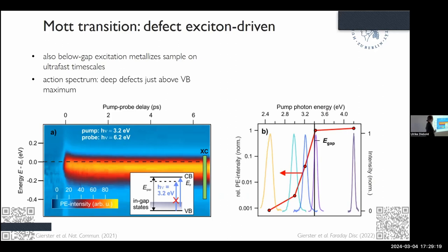And this means that the states responsible for this must be sitting really just on top of the valence band, must be really deep defects. And this also matches this scenario of oxygen vacancies being responsible for this. But of course, zinc oxide exhibits many, many different types of defects.